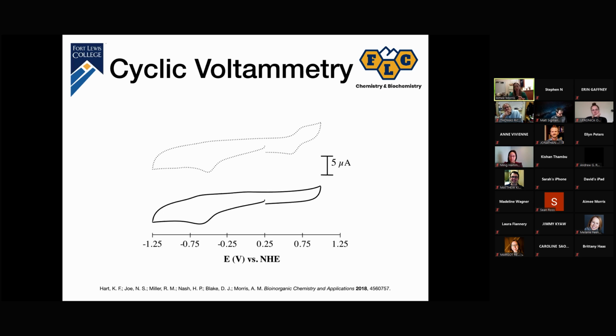But the really important thing about this particular experiment was that you need to have a reduction potential between minus 0.1 and minus 0.5 volts versus a normal hydrogen electrode in water at pH 7 in order to get successful redox cycling within biological systems. And so what we wanted to see, again, we don't know if activation by reduction is happening, but would this complex be capable of being within that redox cycle limit? And what we found is that we have that irreversible reduction of cobalt 3 to cobalt 2 that happens at negative 0.51 volts versus NHE.